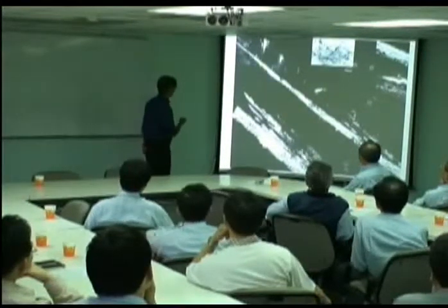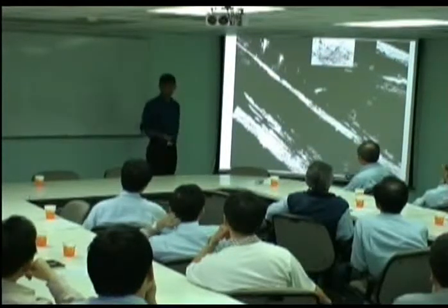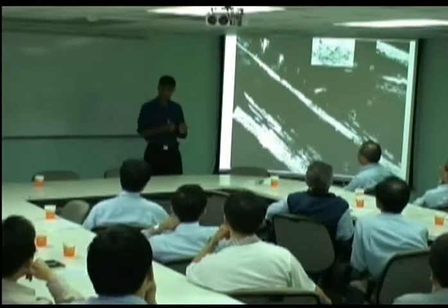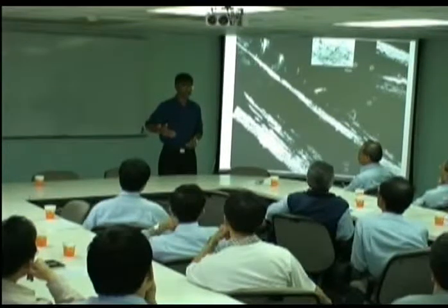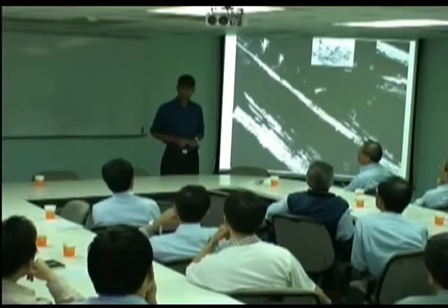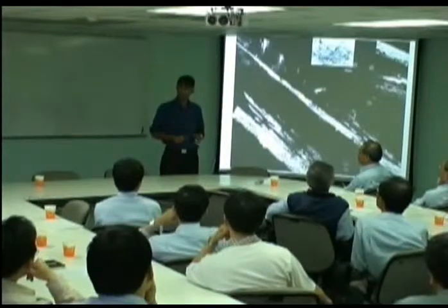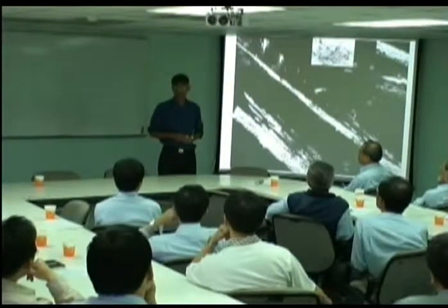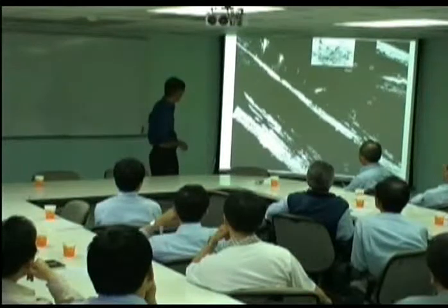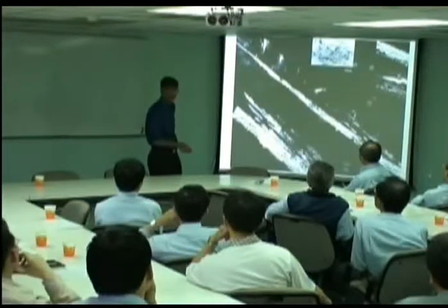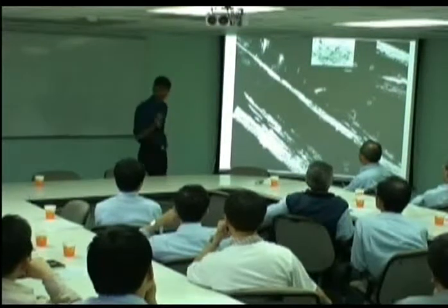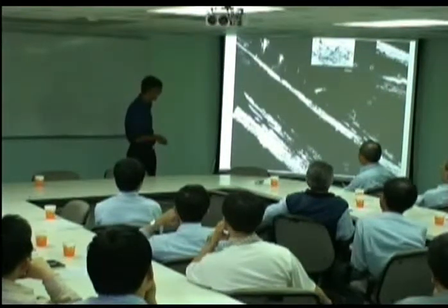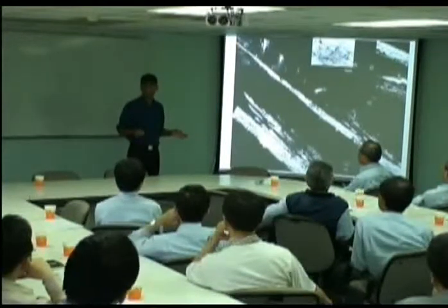So notice that the size of the plate here is the same as the size of the plate here. What's happening is that the shear deformation generates so many dislocations in the austenite that the interface becomes blocked. The plate cannot grow anymore. Now that's very good for mechanical properties, because if this was a martensite plate, its size would be that big, okay? But here, we have a further grain size refining effect, and that is that the plate stops itself.